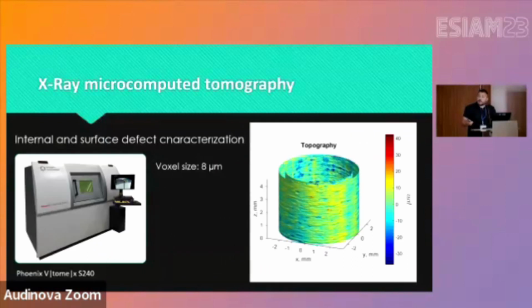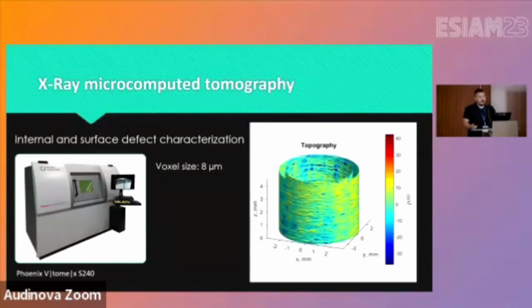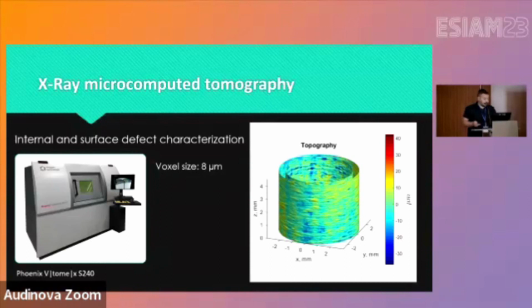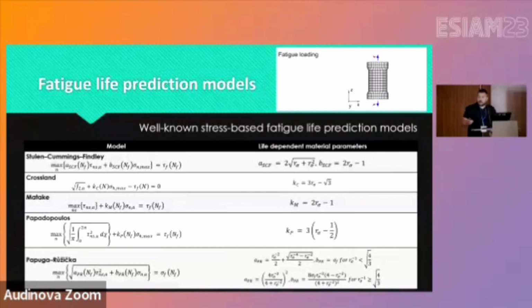After the printing, we used tomography to measure exactly the wall thickness and the void distribution of the printed specimens. The models we used to calculate the fatigue life, other than our Gaussian machine learning model, were the ones here. So Sines, Crossland, Findley, Dang Van, Matake, Papadopoulos, and Papuga-Ruzicka. Most of them use the fatigue limit as the parameter, but we used the life-dependent parameters, because the characteristics were not parallel and the fatigue limit has some limitations. So we use parameters that change with fatigue life.